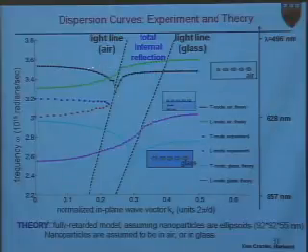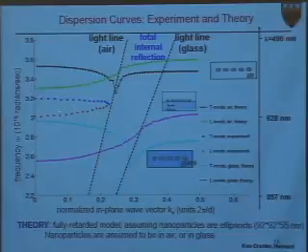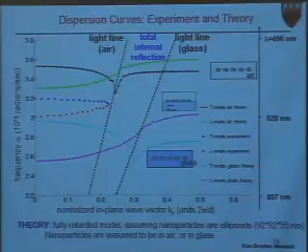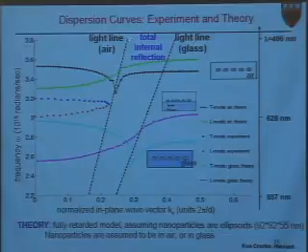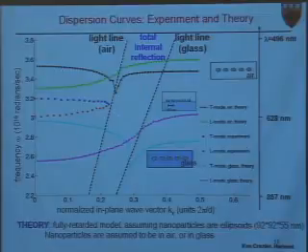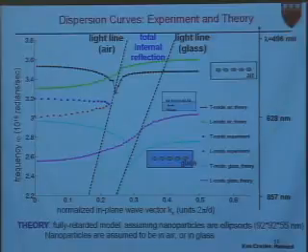And so initially we thought, okay, this seems consistent. In our case, we have nanoparticles at the interface between two media, so our curves are in between these two cases. But what we're interested in doing is measuring beyond this light line of air that we get through transmission measurements, to get the larger k vectors. Because in transmission, all we can get to is a maximum k vector along the chain of 2 pi on lambda. If we come in through the sample with total internal reflection, then we can get up to the light line of glass, 2 pi n on lambda. And this region corresponds to the total internal reflection region that's appropriate for our waveguide application, because we're going to have larger k vectors than the k vectors in air.